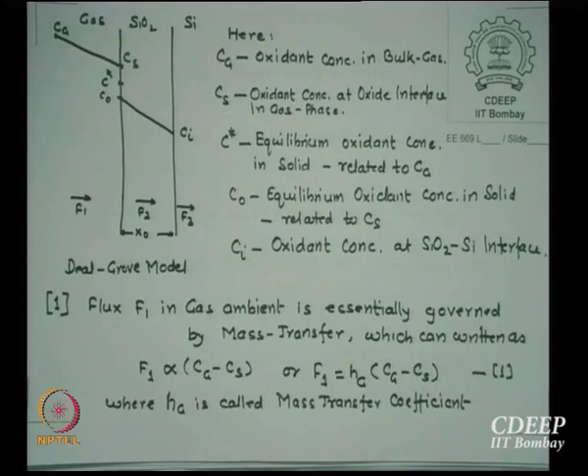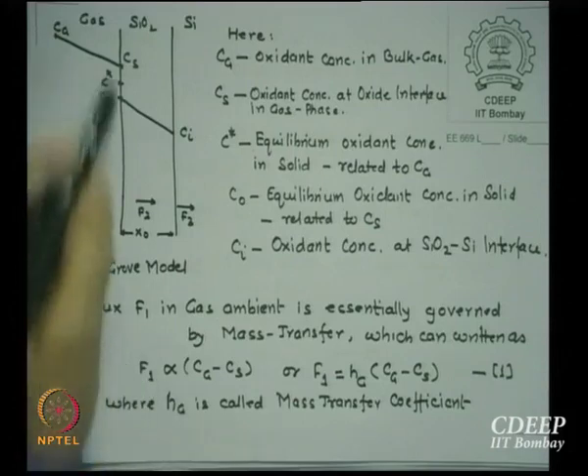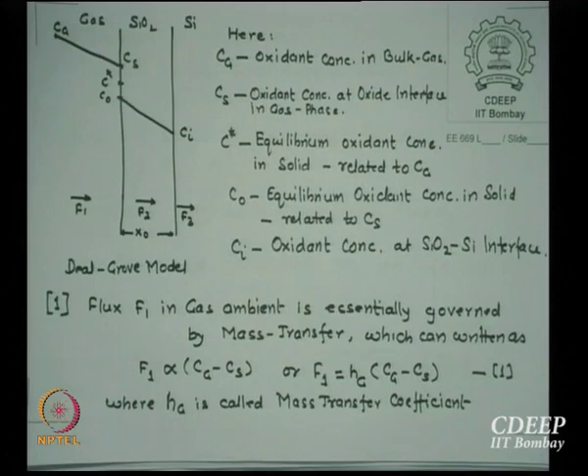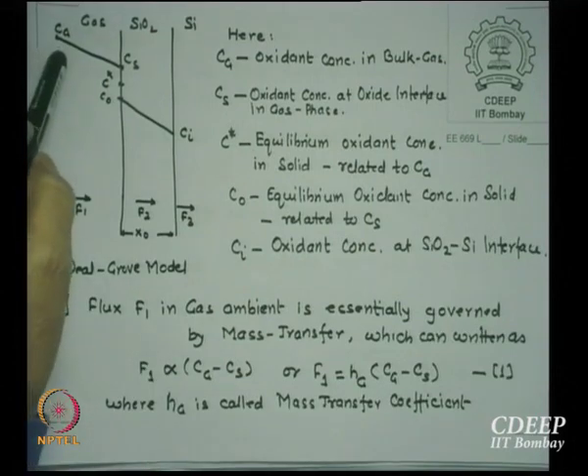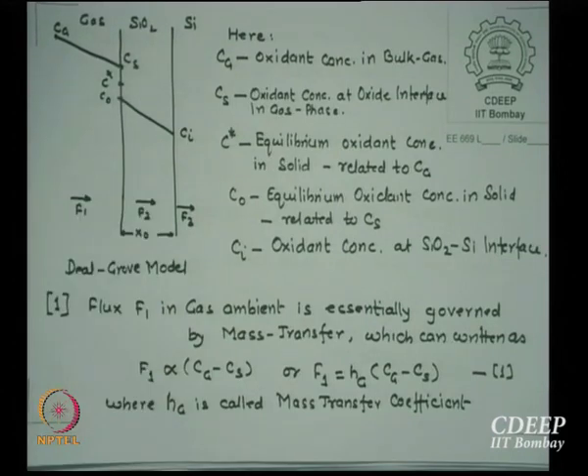According to the Deal-Grove model, flux F1, which is in the gas phase from the ambient to the surface, we know will be proportional to the gradient. If Cg is the gas concentration in the bulk, Cs is the gas concentration near the surface, then F1 must be proportional to Cg minus Cs. Whatever is at the surface and whatever is available in the stream, the gradient is set, and that difference between the two is the flux F1, and the proportionality constant is called the mass transfer coefficient hg. So F1 is hg times Cg minus Cs. This is the first flux which we are looking into, that is the gas phase flux.